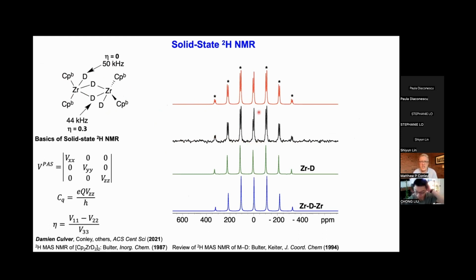This region here is your isotropic chemical shift information that you would report in any supporting information. These spinning side bands appear at integers of the rotor frequency, and the magnitude of these spinning side bands is related to the quadrupolar coupling constant, which is related to one term of the EFG tensor, which is characteristic of the chemical environment of your deuteride. There's also an asymmetry parameter that is essentially how all three terms in this EFG tensor play off each other.